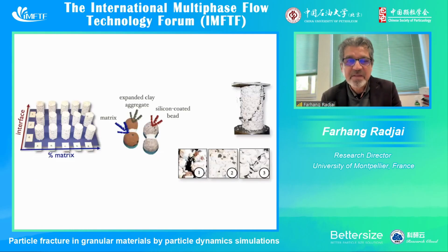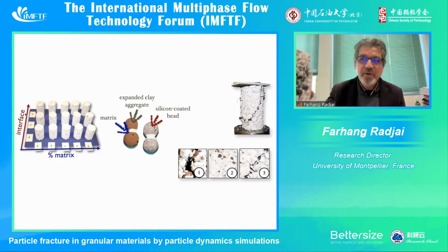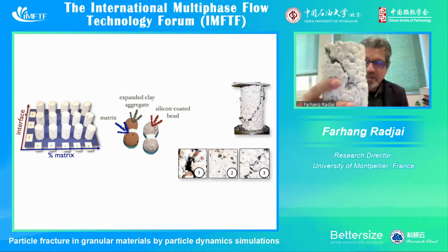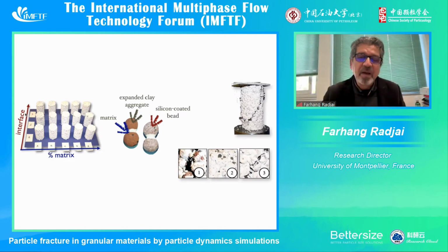For experiments, we used a way to control both the amount of the matrix and the adhesion, by coating the particles using silicon. And of course, the particles are expanded clay aggregates, which break very easily. And we made samples with different values of the matrix and different adhesion. Here I have one example of this, if you can see, which is broken, as you can see, under diametral compression.